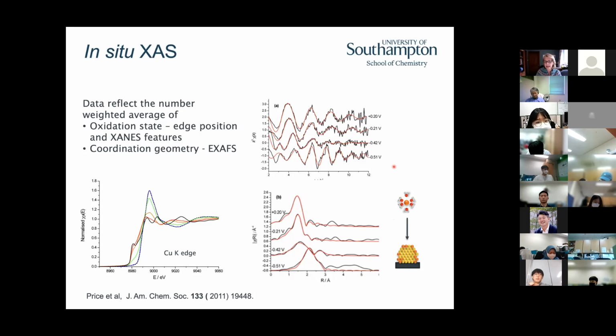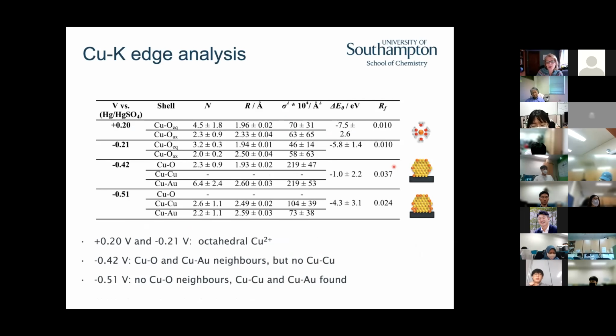And you can clearly see in this set of data the key features in terms of analyzing X-ray absorption spectra. We could fit all the data, right? And these are the parameters you would get out if you fit the data. We had the coordination number. You can see that the errors are pretty large, right? As I said, because it's always coupled to this Debye-Waller factor. But for the distances, we know them quite precisely, which is why we can confidently say that there are 2 different oxygen distances around those copper ions, right? And you can see that as we go more negative, we lose the oxygen coordination and we gain copper-copper. And we gain copper-copper when we have the highest coverages, but we initially just have copper on the gold.